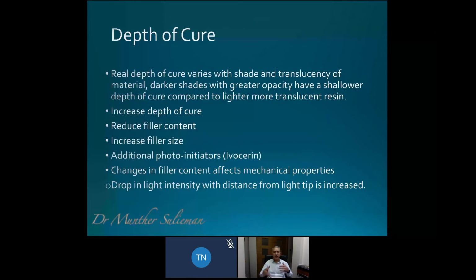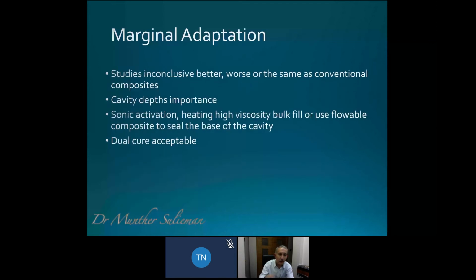So this depth of cure business is very, very important. The problem for bulk fills is they want to make sure that the whole cavity is cured. So there's a trade-off. They either reduce the filler content, making it weaker, or they increase the filler size, or some companies add different photo initiators to their product. So there's a number of different things. And remember also there's a drop in the light intensity with distance from the light tip to the bottom. So there's a number of different issues in terms of the depth of cure. We'll talk a little bit about Aura bulk fill in a minute in terms of how they get past that problem.